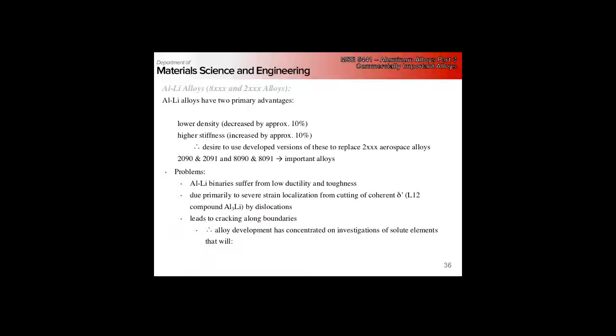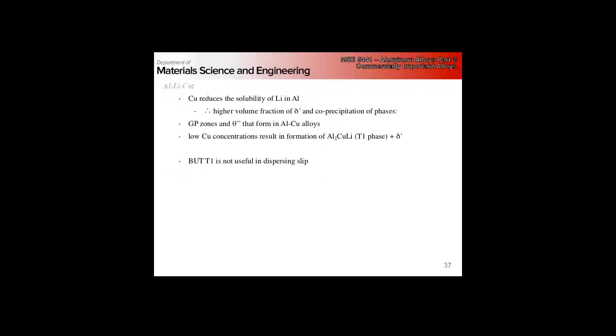We end up with cracking, and so the focus on developing aluminum lithium alloys is we want to form additional precipitates that promote homogeneous deformation. So precipitates that are not so easily cut, that are going to give us a better dispersion of slip. Remember, as we shear these particles, we're creating a weak spot. Under fatigue, when we're ratcheting our stress, we're going to keep slipping on those same slip systems leading to slip bands where those particles have already sheared.